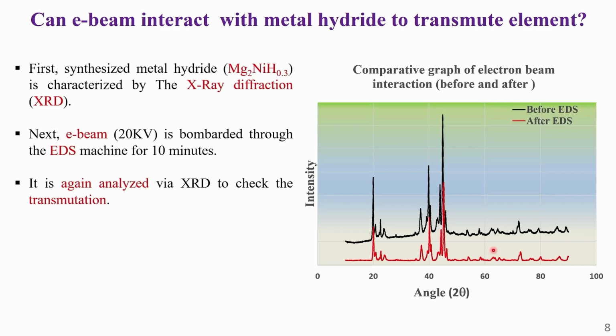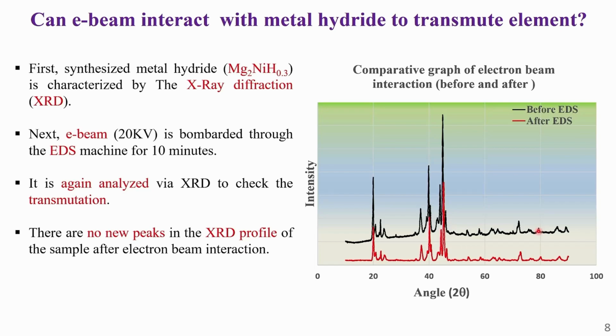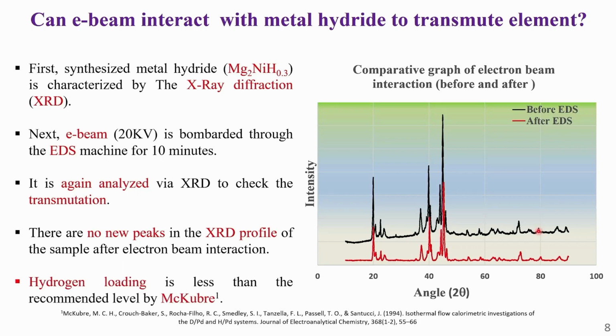The black lines correspond to XRD results prior to the electron beam exposure and the red line shows the results after. It can be observed that no new peaks show up after the electron beam exposure, which points towards the conclusion that the exposure of the hydrated metal sample to the electron beam used in the EDS analysis does not cause transmutation. It might be worthwhile to note that the hydrogen loading in the control sample used is much less than the recommended loading suggested by McKubre for observing excess heat.